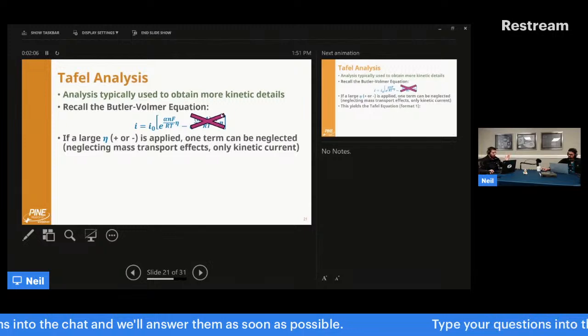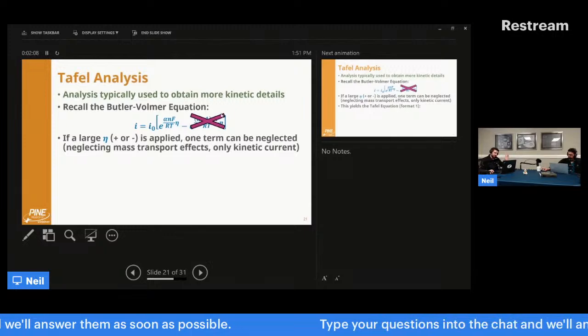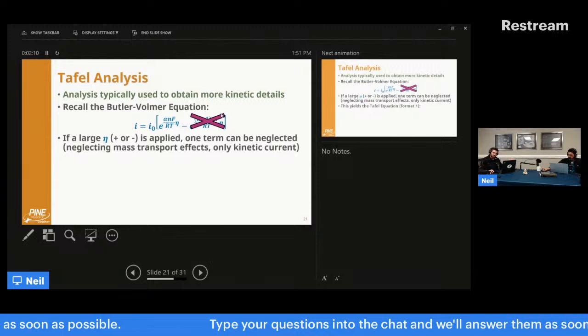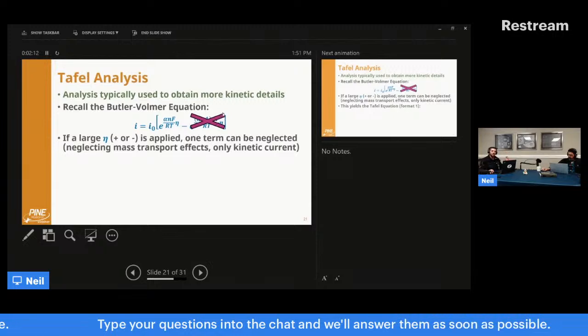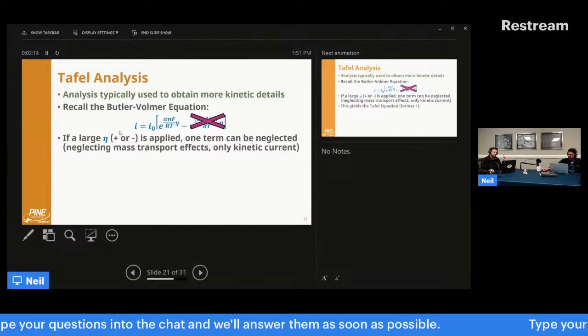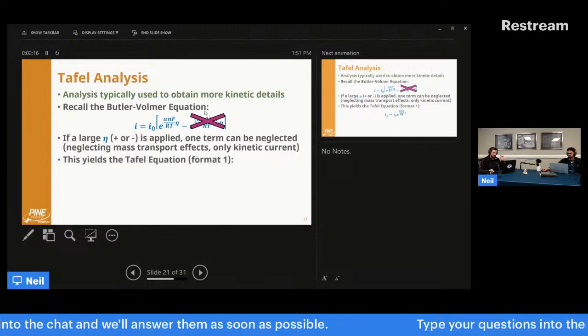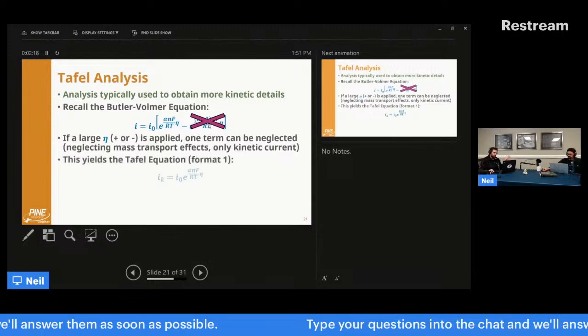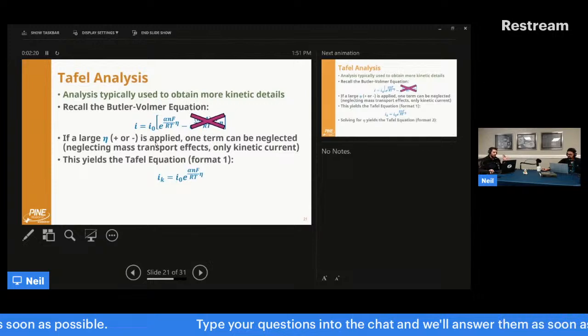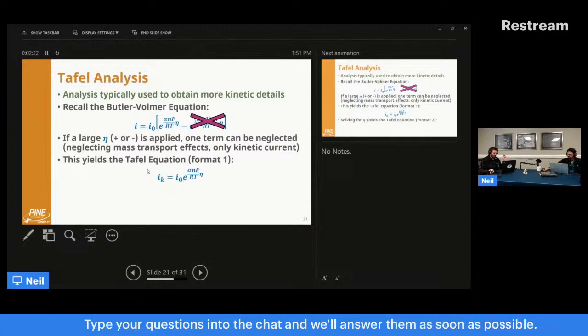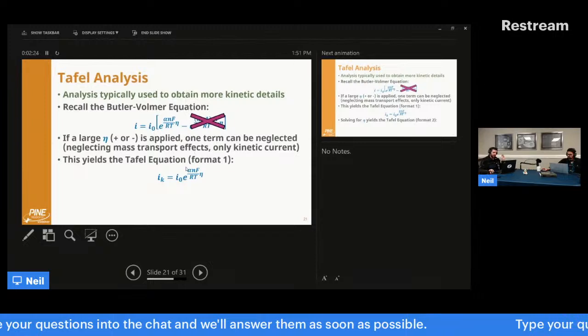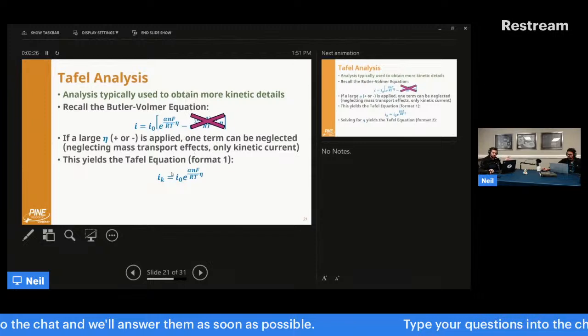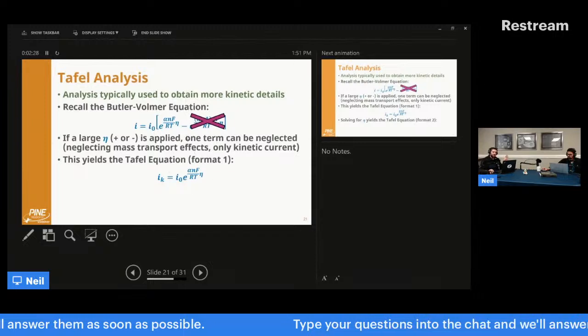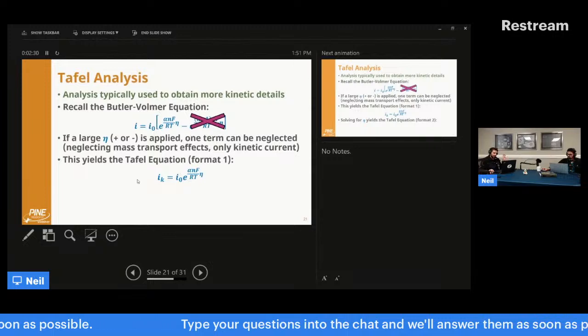If I have a really, really large overpotential positively, I have very strong oxidation happening and no reduction. It's fully irreversible. I can neglect one of these terms. So assuming I'm neglecting this one, you could do it for either way. It doesn't matter. Then what I get is the Tafel equation, from which you get the Tafel slope. The Tafel equation is half the Butler-Volmer equation, and this is its form. So it's just these terms here.